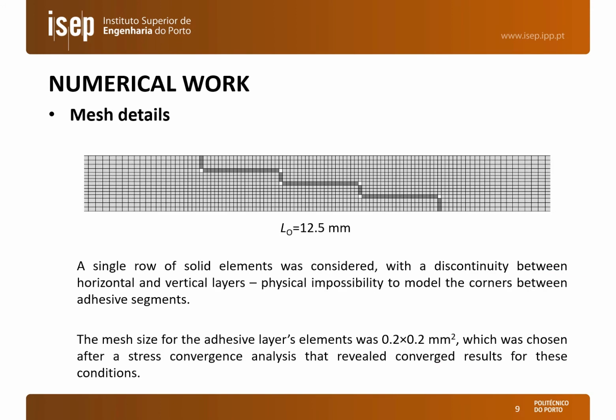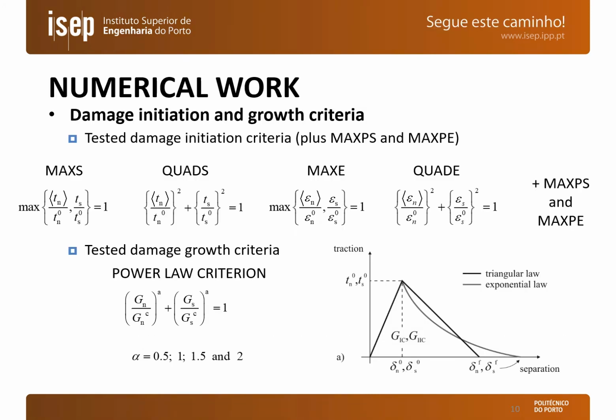We can see here an example of mesh details for a joint with an overlap length of 12.5 millimeters. We can see that we considered only a single row of solid elements to model the adhesive, but with a visible discontinuity between the consecutive vertical and horizontal adhesive layers, and this is because of the physical impossibility to model these corners in this methodology. The mesh size for the adhesive layer was elements with a size of 0.2 millimeters.